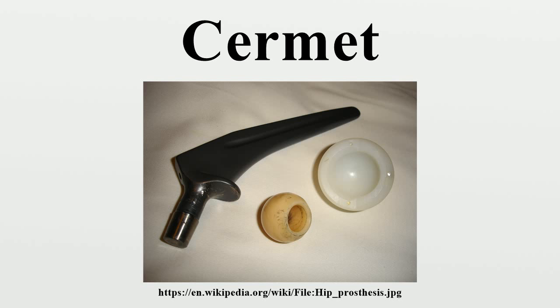Depending on the physical structure of the material, cermets can also be metal matrix composites, but cermets are usually less than 20% metal by volume. Cermets are used in the manufacture of resistors, capacitors, and other electronic components which may experience high temperature. Cermets are used instead of tungsten carbide in saws and other brazed tools due to their superior wear and corrosion properties. Titanium nitride, titanium carbonitride, titanium carbide and similar can be brazed like tungsten carbide if properly prepared, however they require special handling during grinding.